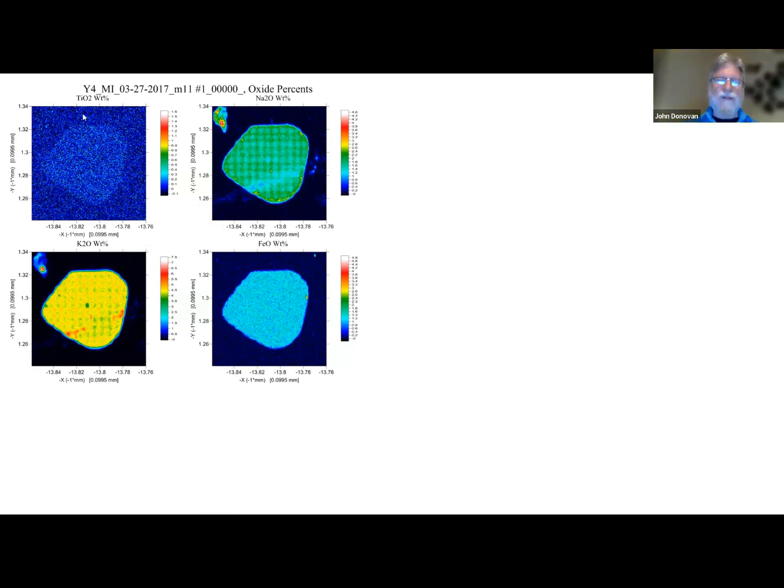So what's happening here, and I talked to Ben Hansen at Corning Glass, who was one of the people who developed the Gorilla Glass that's in all our cell phones, and that's a very high alkali rich glass, which makes it shatter resistant. He says that what this is caused by is that you've got this moving beam, and then you're dragging along the subsurface electron charge. So I should say you've got this moving subsurface electron charge that is dragging this sack of sodium and potassium ions. And every once in a while, that envelope of ions gets too big, and it just drops off and drops off. And it's an amazingly regular process.